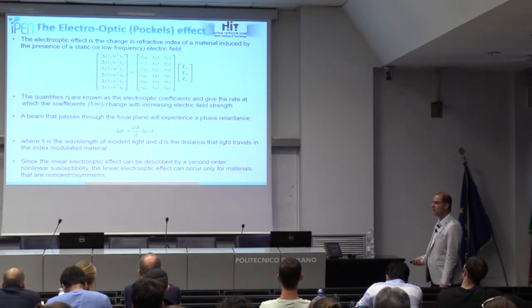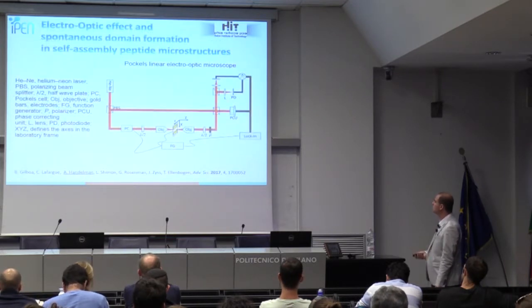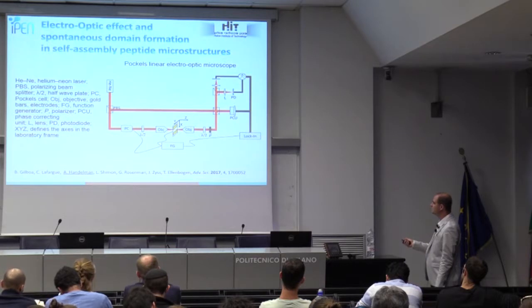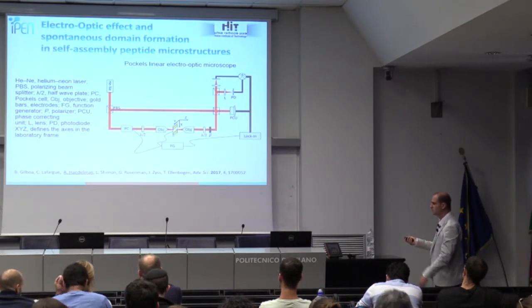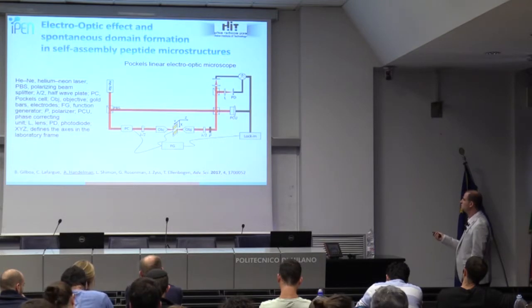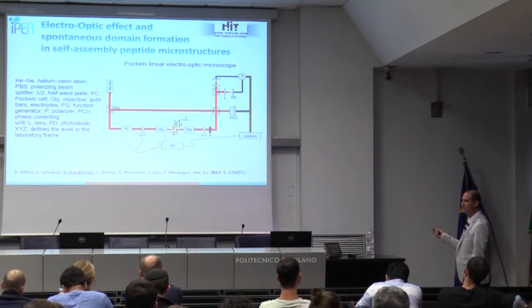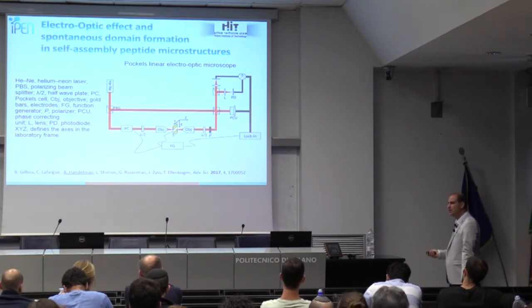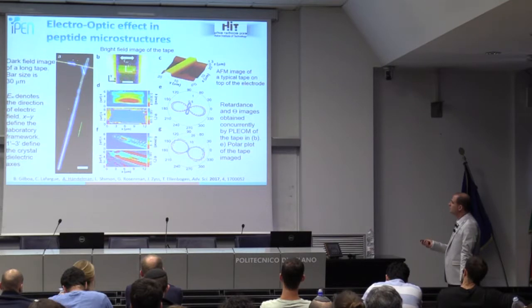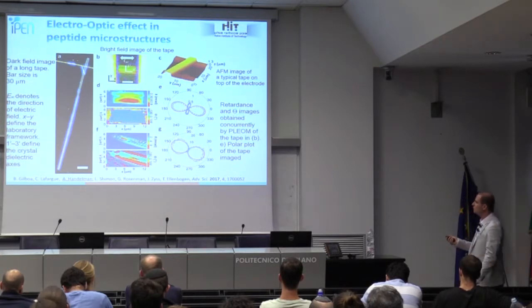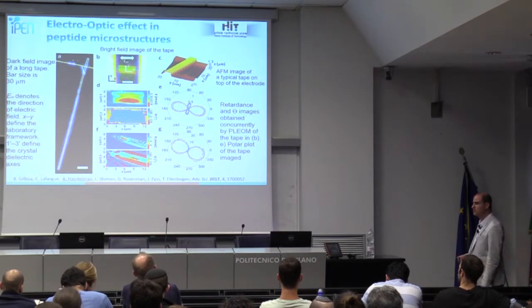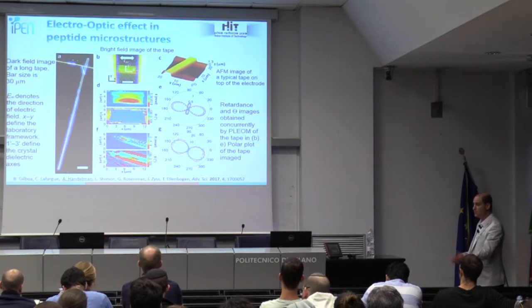Okay. So here we use a special technique known as Pockels linear electro-optic microscopy, which is actually some kind of Mach-Zehnder interferometry microscope with Pockels cells. Okay, I will explain the Pockels cells to you later. So here the two arms recombine, and there is a phase and amplitude of the images. Okay, we use this to understand how strong the electro-optic effect is. So if we take a peptide tube, for example, which is very long, as you can see here, and we use it in the microscope setup that you saw earlier, we apply an electric field.